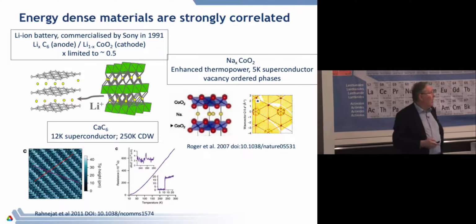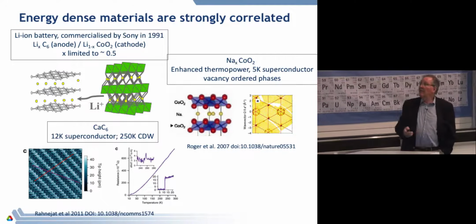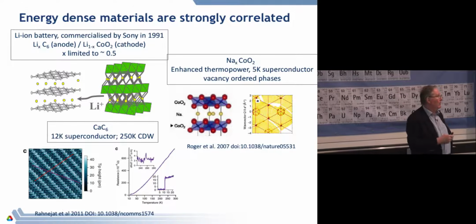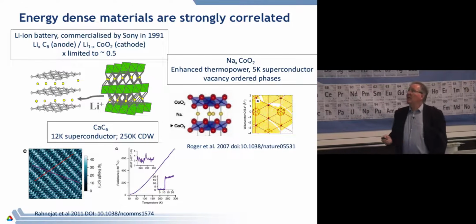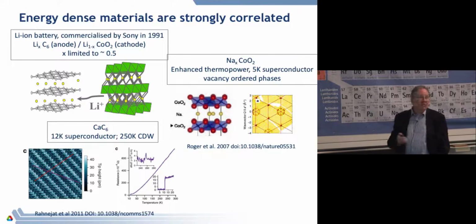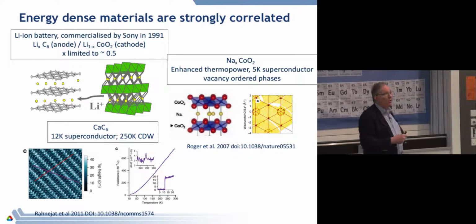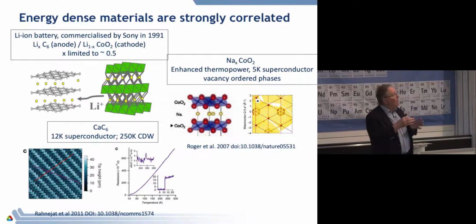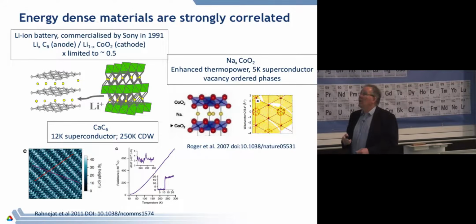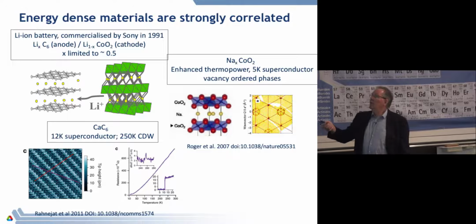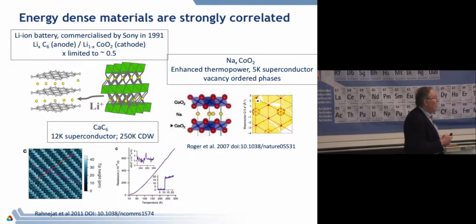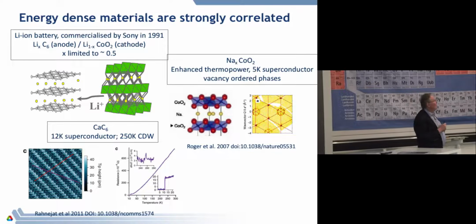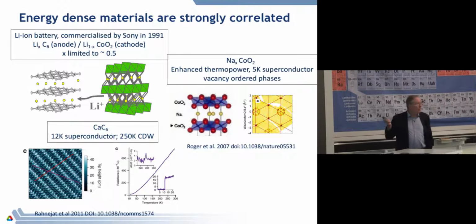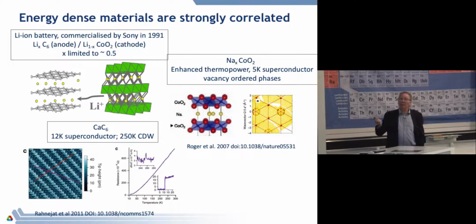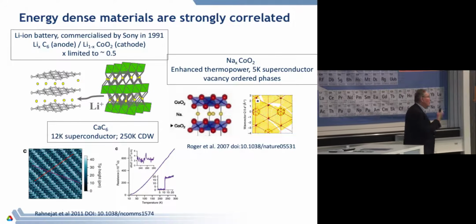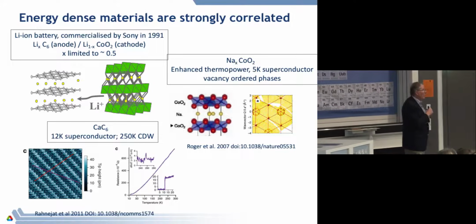Okay. And what you're running into here, in this case, is what I would call Mott physics. Because the phase transitions which are happening in some of these structures are phase transitions in which carriers become localized, and those localized carriers form new phases, and those new phases are often insulating. And because those phases are insulating, they are not very good things to make electrodes out of. The first thing you need from your electrode is that it be a metal.